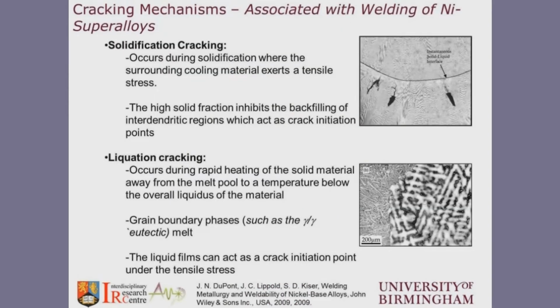Basically, nickel superalloys, when we weld them, they are typically exposed to, or can be prone to, 4 mechanisms of cracking. The first one is solidification cracking, and that's similar to cracking that we see in many other materials, not just nickel superalloys, where typically the freezing that happens combined with the segregation that's happening during solidification results in...